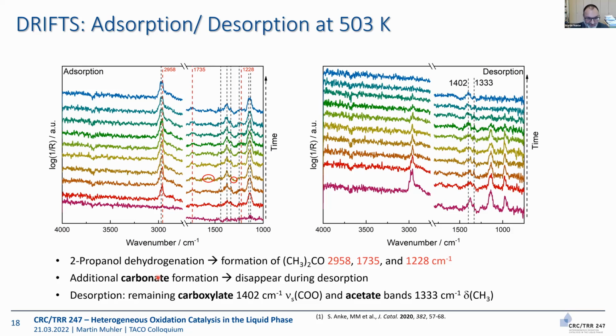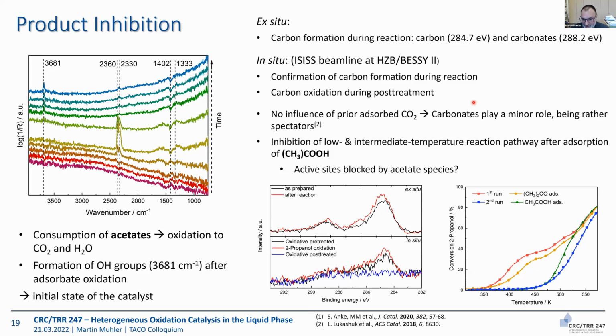And the other species that was interesting, that is, of course, carbonate. That was the first guess, what else should be formed. But in addition, we saw carboxylate, also the symmetric stretch vibration of the OCO group at 1402 wave numbers. And this band here in addition, and that allowed us to identify acetate. So these bands here, not that large, but reproducibly formed. Now, chemically, when you start wondering acetate, what does that mean? Acetate means you break one CC bond in addition. It's a C2 species, and it's rather plausible that acetate is an intermediate on the way from propoxide species to CO2.